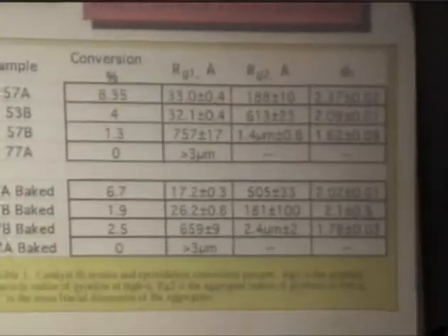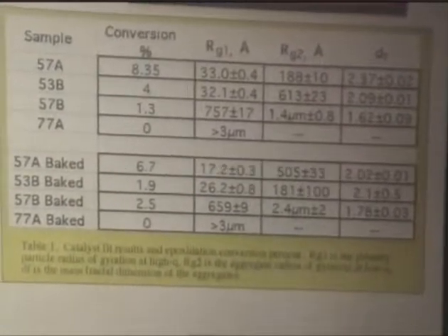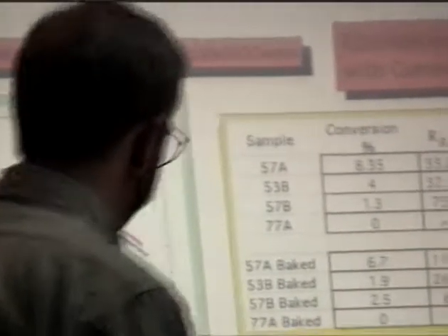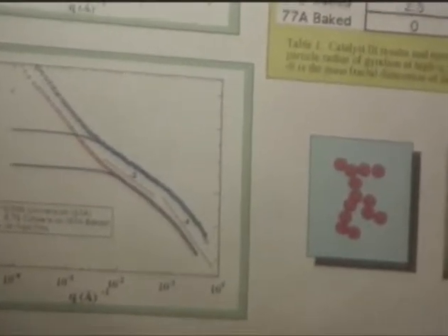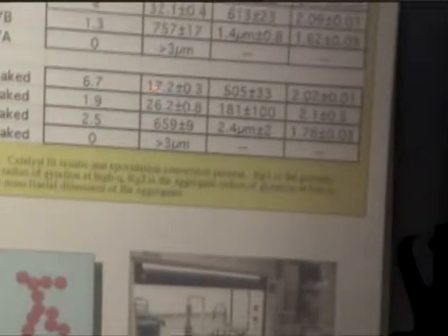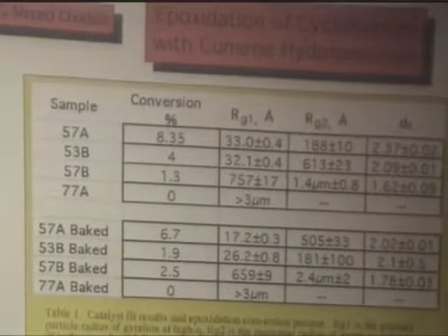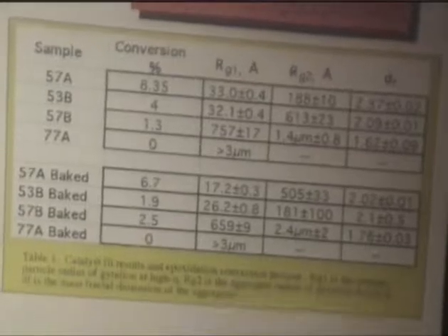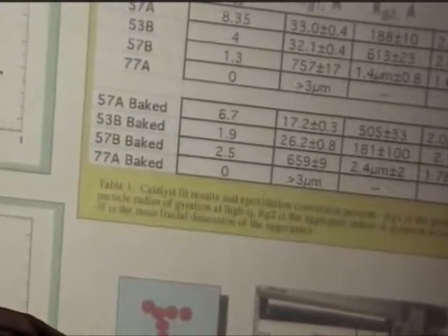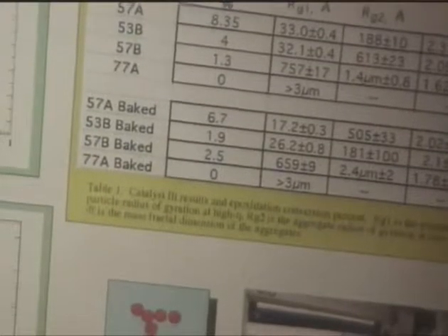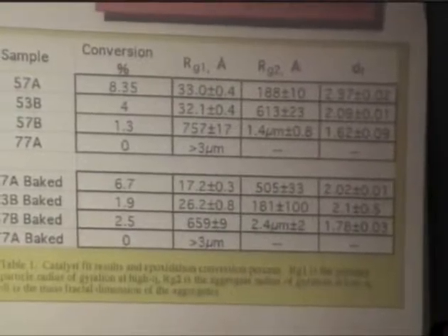Okay, so when you bake it at mild conditions, and this is baked at 140 degrees under vacuum for 24 hours, and nothing severe, just still amorphous. The reactivity changes, and also the strange thing is that these sizes get smaller. And I showed you earlier that the surface area for the pure silica systems made with this laminar flow reaction got smaller as you baked it at mild conditions. In this case, the surface area increases basically. That's what this is saying.